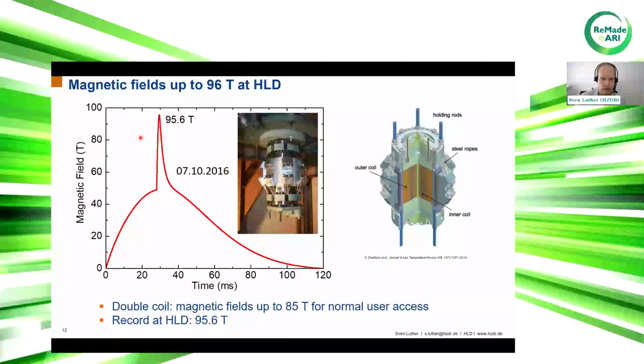Our record of highest created magnetic field in our lab was in 2016, where we created 95.6 Tesla, and this was done in a so-called double coil, which you can see here in the sketch. So we have an outer coil, which is creating the typical pulse field shape, which I've already shown before. And on top of this, we have the inner coil giving the peak to reach the maximum field of almost 96 Tesla. But in our normal user access, we are running this double coil at fields up to 85 Tesla.